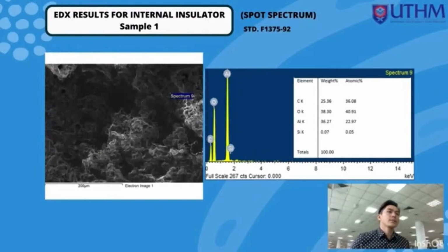Next is the first sample of the internal insulator. Given with the spot spectrum, we found the elements carbon, oxygen, aluminum, and also silica, and found different weight percentages. So the oxygen also takes the highest weight percentage.